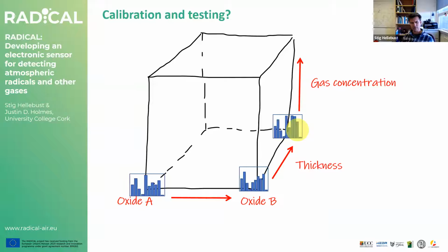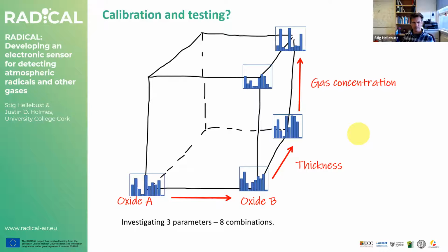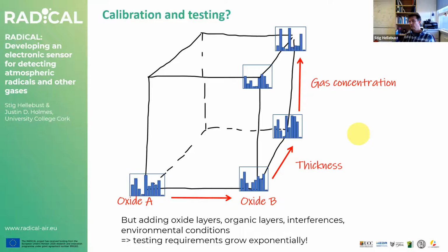And so far, we have only tested in clean air, say, zero air. So let's say we add some NO2, and you get a response from the different signals, a different profile. But it's not given that if you expose it to that same gas concentration with a different thickness of that layer, you won't get a completely different profile of responses. So these are all things that we have to investigate. And here, if we just have three parameters: oxide type, thickness, concentration, you end up with at least 8 different tests to do. And of course, we have to start looking at all the different organic layers, how they all interfere, how they all respond to other gases, because of course the atmosphere is full of interferences, and all the environmental conditions. So the testing requirements grow exponentially.